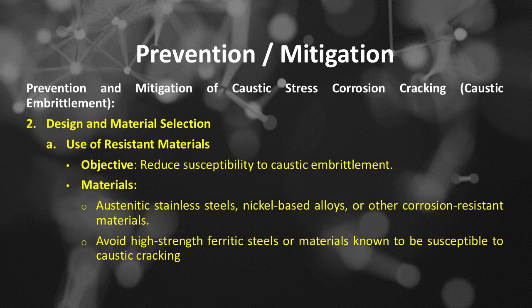Number 2 of prevention and mitigation of caustic stress corrosion cracking or caustic embrittlement is design and material selection. Number A, use of resistant materials. The objective of using resistant materials is to reduce susceptibility to caustic embrittlement, for example, austenitic stainless steels, nickel-based alloys, or other corrosion-resistant materials. Avoid high-strength ferritic steels or materials known to be susceptible to caustic cracking.